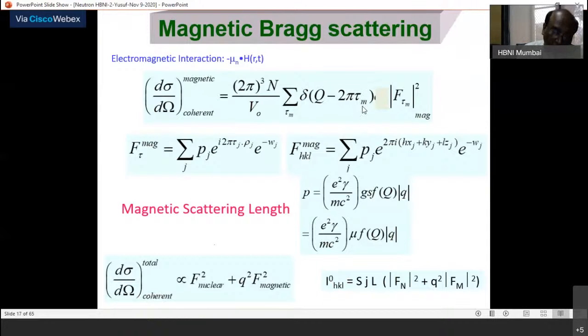That I have given you as an example on the very first day. Let us say for certain antiferromagnetic material, certain new Bragg peaks do appear at a different 2 theta, while in the paramagnetic phase, while the sample is not magnetically ordered, moments are not magnetically ordered, those peaks are absent.